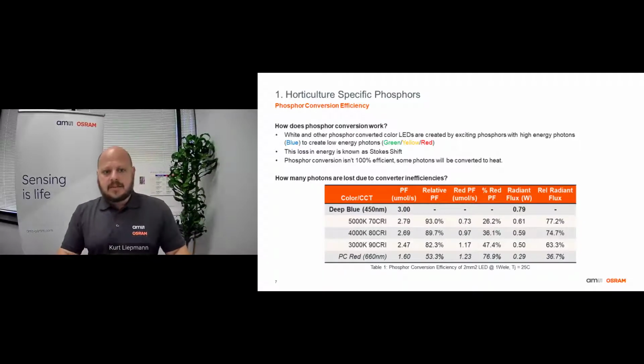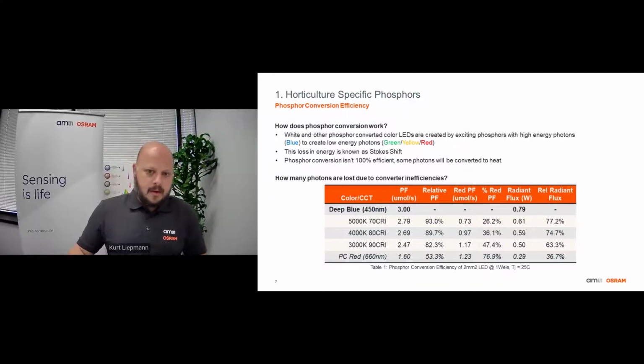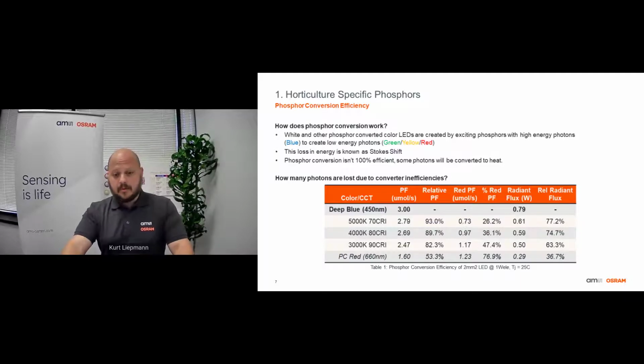So if we look at the last 2 columns in this table, we can now see the impact of Stokes shift on the LED's radiant flux. While photon flux is the important metric for horticulture, as I mentioned earlier, LEDs are typically measured in radiant flux. So the radiant flux output of each of these LEDs compared to its blue pump is lower than the relative photon flux that is being emitted. So for example, while a phosphor converted red has 53.3% of the photons remaining that the deep blue had, the total energy that's being emitted is only 36.7% of that bare LED.